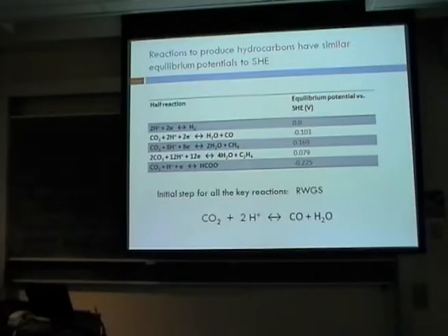You can do Fischer-Tropsch chemistry over iron catalysts where you polymerize carbon monoxide in order to make diesel fuel, for example. And so synthesis gas can be a valuable stream in itself that can be integrated into existing petroleum refineries, if you can even just do this first reaction that's required for all the others. Although ultimately, from an efficiency standpoint, it would be better to directly produce longer hydrocarbon chains.